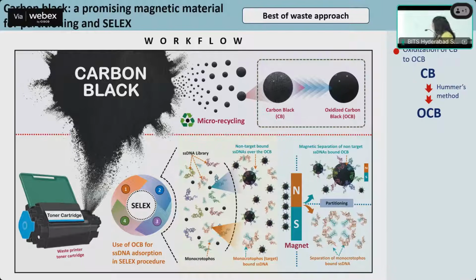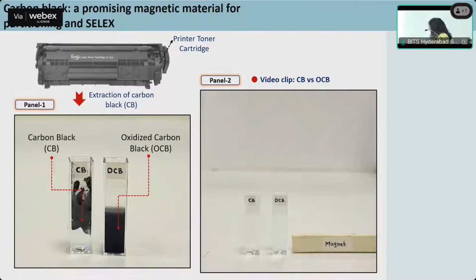In this case, the ssDNA library was incubated with the target pesticide. Later, it was mixed, and we added the material, which is OCB here, mixed it, and then the magnet was brought close to the wire. It pulls all the non-specific material, and we have the enriched pool, which we will utilize for the Selex process. This is what CB looks like in the aqueous solvent, while the OCB, the oxidized carbon black, is completely soluble.